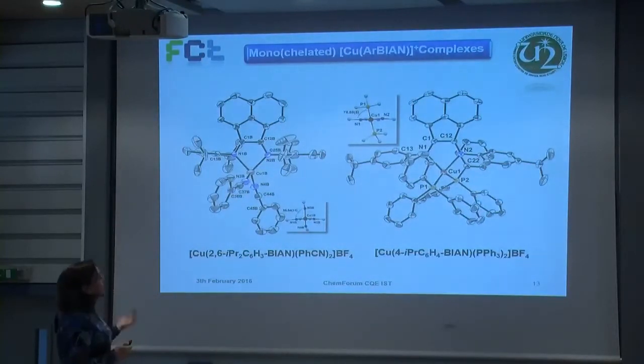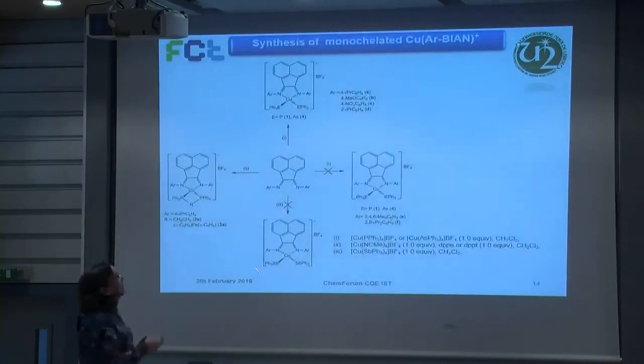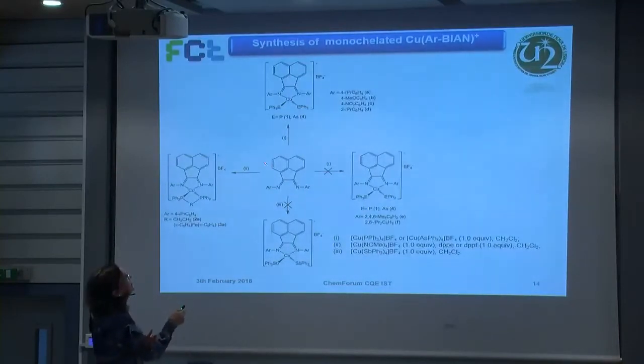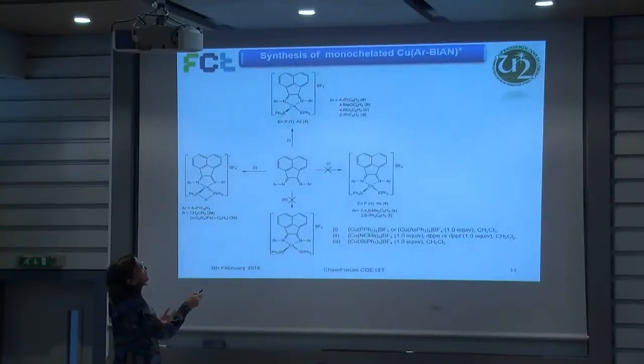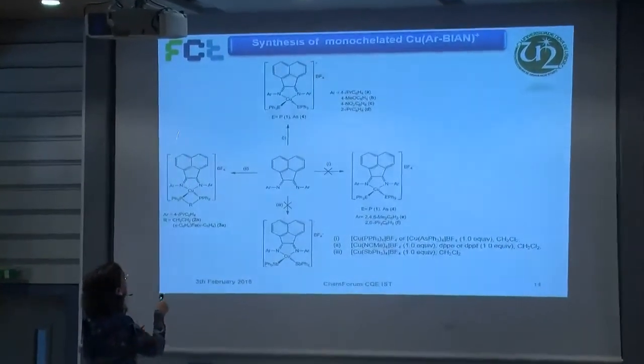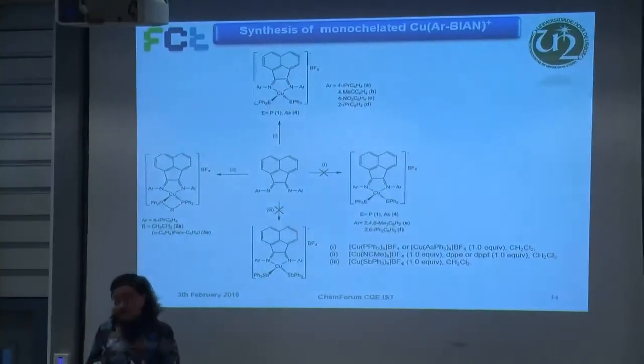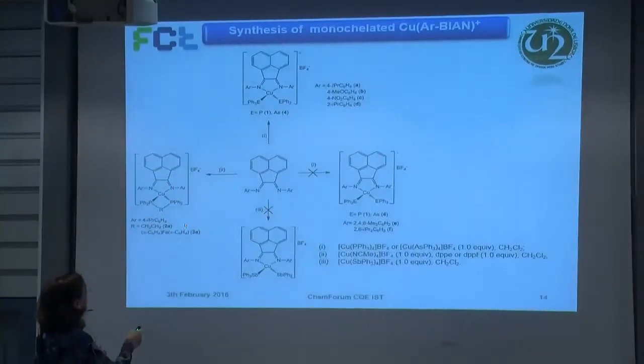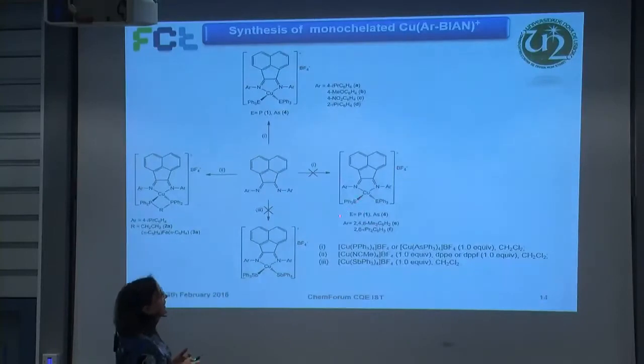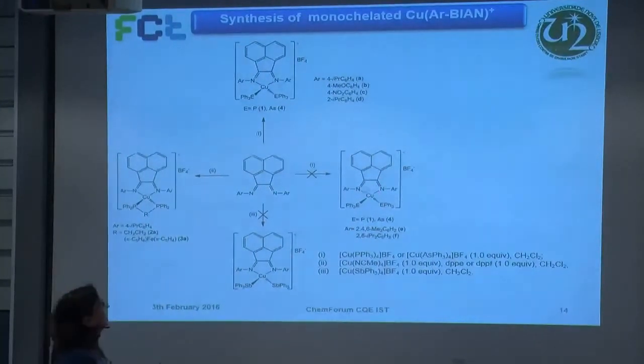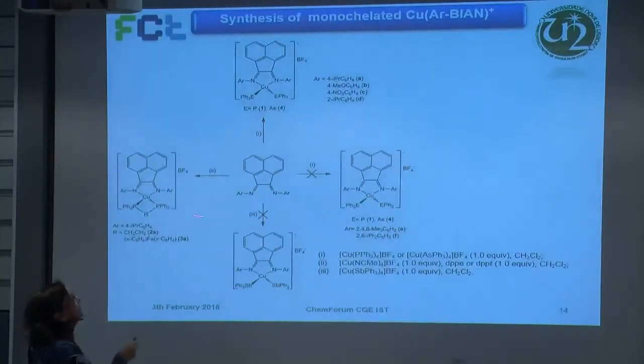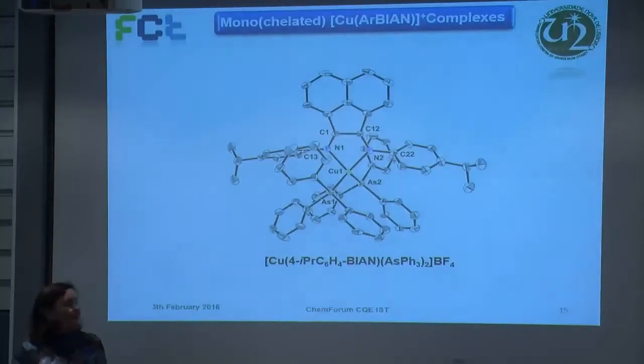Okay? We continued synthesizing all kinds of complexes, changing the R substituents by, for instance, 4-isopropyl, 4-methoxy, 4-nitro, 2-isopropyl. In this case, with chelating diphosphines, and even with ferrocene. We also tried with stibines and arsines, and with these routes we couldn't get the results. So we already had quite a large number of cationic copper(I) complexes. Here, for instance, is the arsine with two arsines, and with the 4-isopropyl, as you can see here.